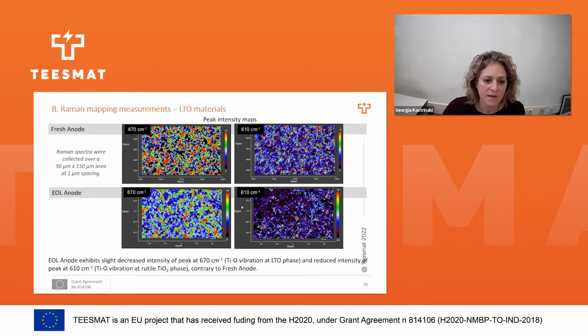And these are the mappings that we obtain. So again, it's not like we have a decrease of the intensity if we compare the fresh and the cycled spectra, but what we see is that we have a higher concentration of the regions having the LTO. We can also see that part of the 610. So we have larger areas of red. So it's not that homogeneous anymore. So we have alterations of our chemical structure.